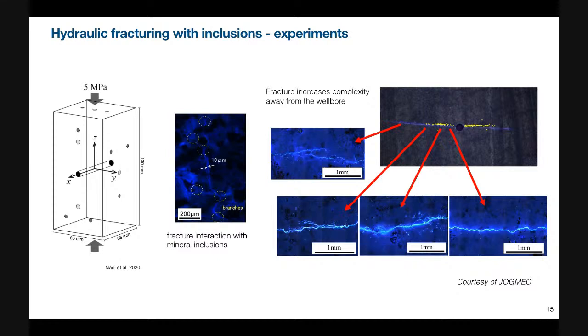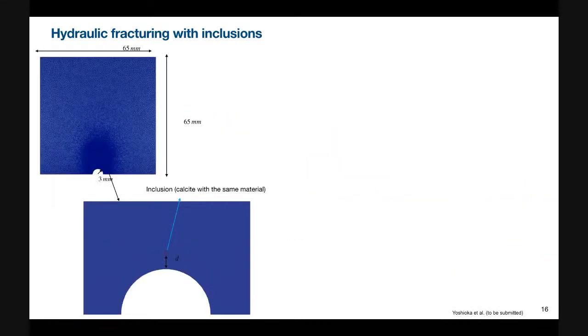And an interesting observation we made is that as the fracture propagates away from the wellbore, it seems to increase in complexity. Near the wellbore, it's relatively straight, but as it propagates away from the wellbore, it starts deflecting more or branching more. And we tried to simulate this, to find out what's going on using numerical simulation.